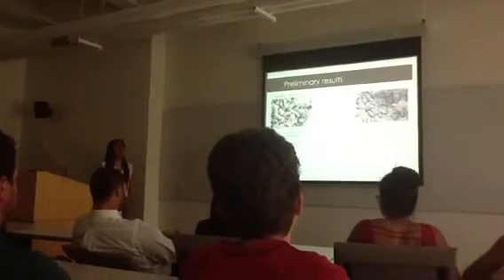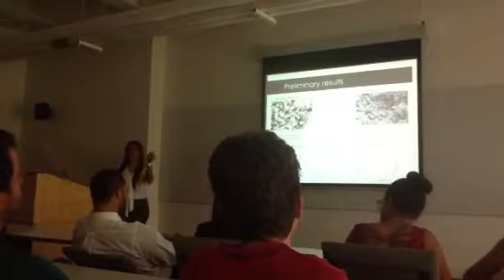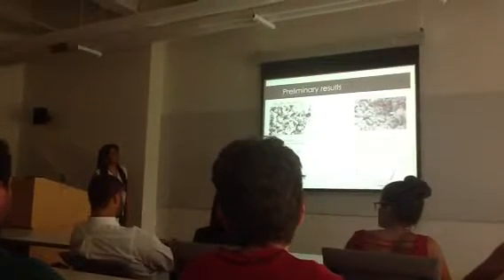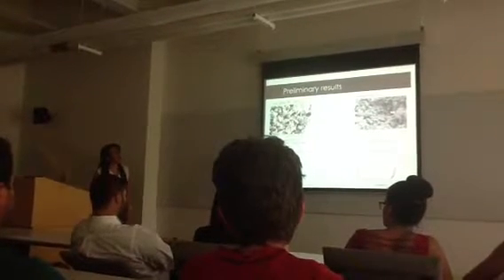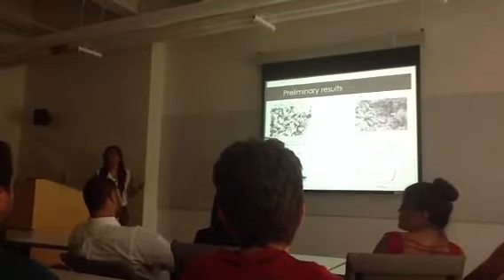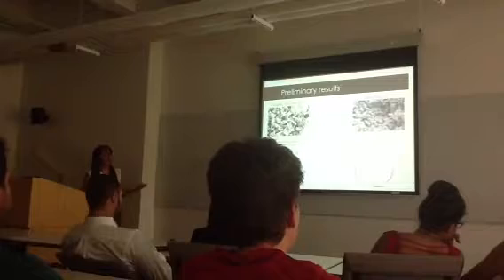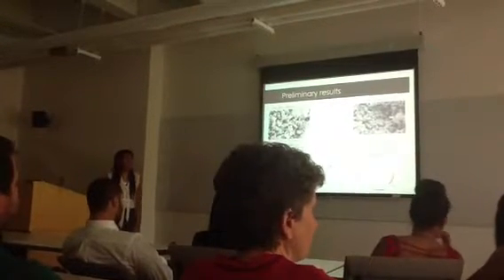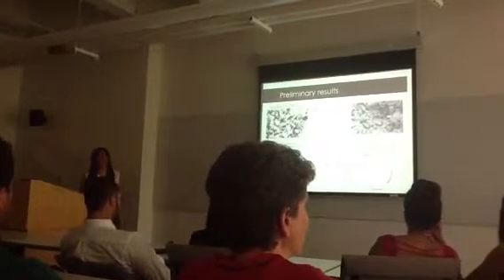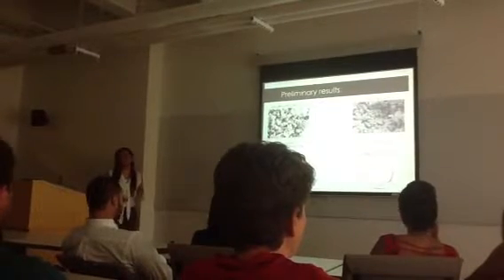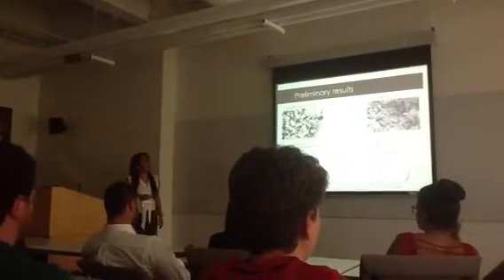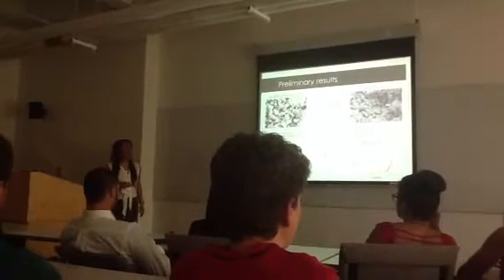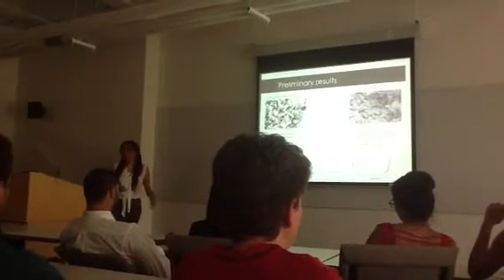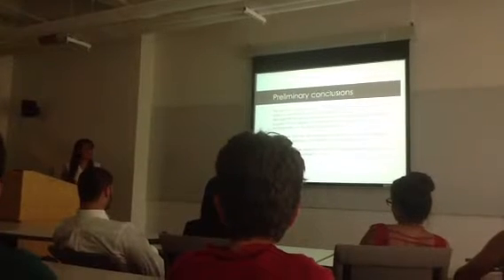So this is my table with all the results and triplicates, the ones that I have until now. And this is also one preliminary result that I want to share with you, performed in collaboration with my grad student. He did the scanning electron microscope images of these two catalysts, in which you can observe a clear difference in the morphology between the different materials. And I put here my cyclic voltammetry results, in which you can also see a clear difference in the electrocatalytic behavior of the materials. So this suggests that at some point we can correlate the molecular structure of the material with its morphology, and also with its catalytic activity.